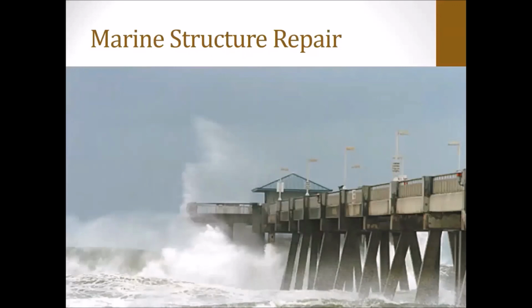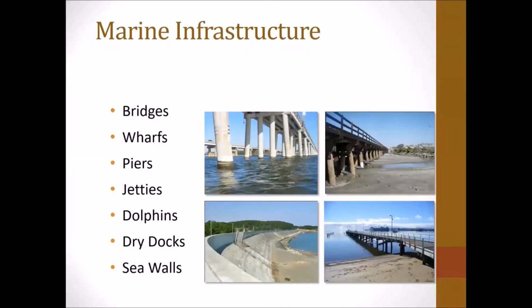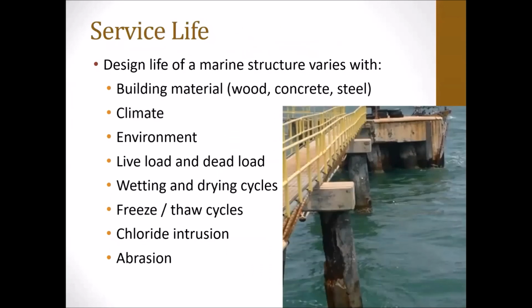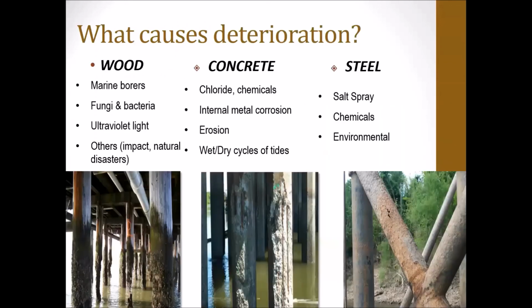I touched a little bit on marine structure repairs. The reason is it's very vulnerable in the tidal zone. We have bridges to sea walls to protect. When you come to building materials, we have wood, but of course not much popular in Sri Lanka. We have wood piles, concrete, steel, and they will be damaged by chloride, abrasion, wetting and drying cycles in the tidal zones. So what causes deterioration? For concrete, chloride chemicals and internal metal corrosion. For steel, salt spray.